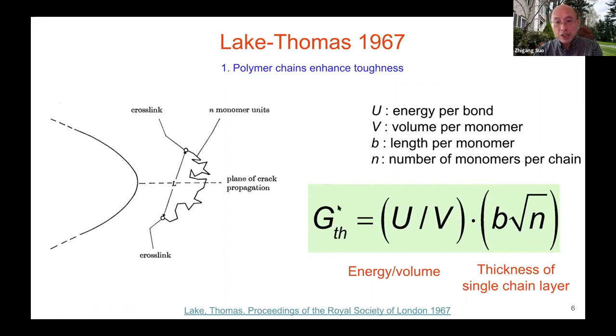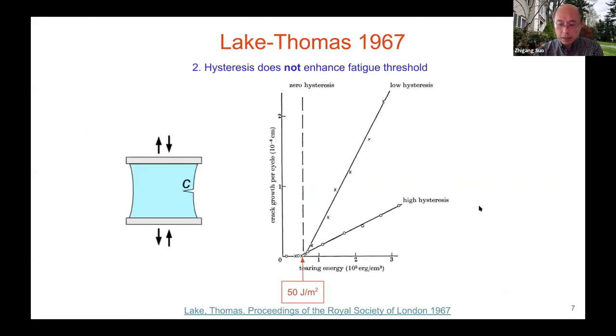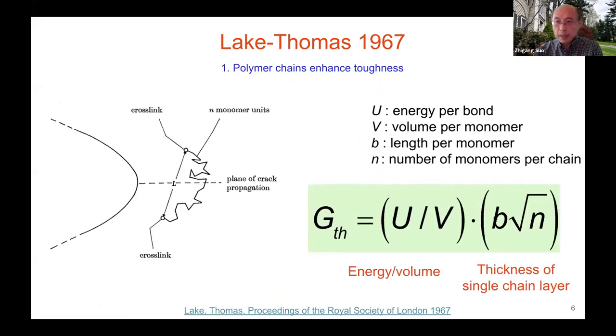Therefore, the energy, so I won't explain this symbol, but this is energy per unit area. This is energy per bond, this is volume per monomer. So this has a unit of energy per volume. You need to multiply by the entire thickness.